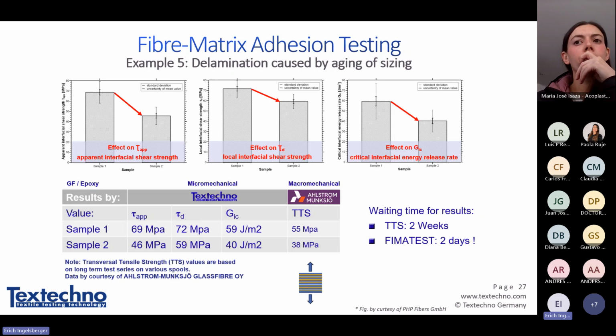Here you can see between sample 1 and sample 2. Sample 1 is the fresh, right sizing, and this is the wrong sizing. You can see big differences in the apparent interfacial shear strength, the local interfacial shear strength, and the energy release rate. This was measured by Ahlström, so they could also get the results, but as I said, with a delay of 2 weeks.